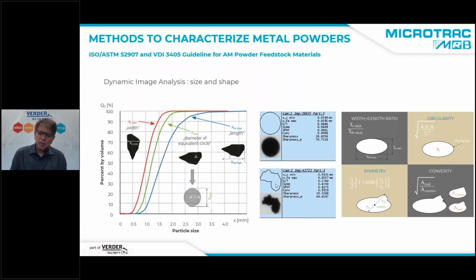The dynamic image analysis very often allows us to see the picture of the particle, and we can see the numbers which are calculated for this single particle. And we can calculate, of course, the size of the particles, but also numbers which describe the shape of the particles. For example, here the width to length ratio, and this tells us, yes, we have nice round particles, or no, we have irregular shaped particles, we have satellites on the particles, and we can see whether the quality from one batch is the same as the quality of the next batch.